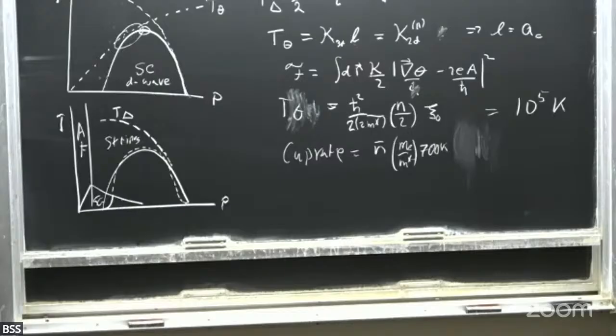So, most of his data is on the order of 1/10 of an eV, which is 1,000 Kelvin. So, my colleague, Tom Devereaux, does determinantal quantum Monte Carlo calculations on the Hubbard model. And in the range of temperatures that he can reach, which is maybe down to 500 Kelvin or something, he calculates the optical conductivity, and you see power laws that look just like Dirk's.